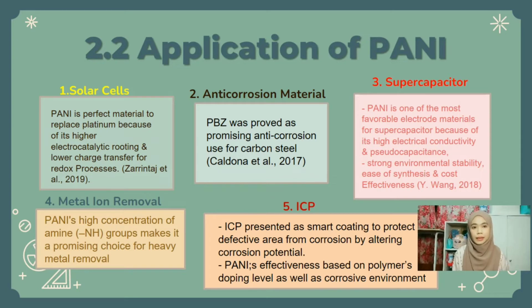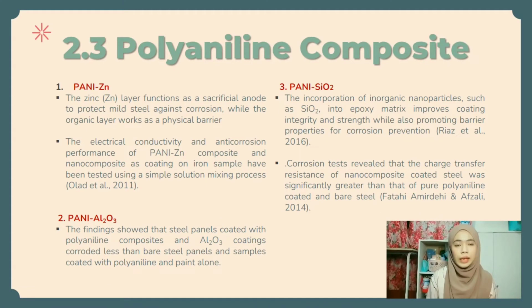The next one is the metal ion removal. PANI's high concentration of amine group makes it a promising choice for heavy metal removal. Intrinsically conductive polymer, ICP, presents as a smart coating to protect defective area from corrosion by altering corrosion potential. PANI effectiveness is based on polymer doping level as well as corrosive environment. The next one is the polyaniline composite.